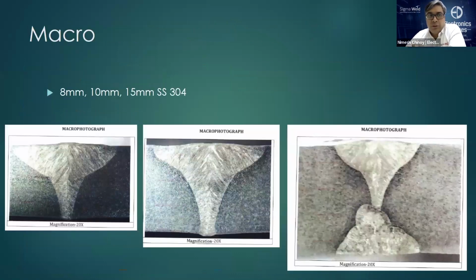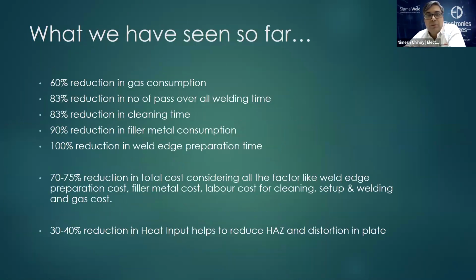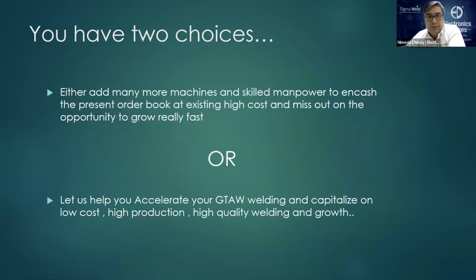Some of the macrographs for 8, 10, and 15 millimeters. If you see, 10 millimeters is in a single pass, 15 is done in 3 passes, 1 on the top, 3 on the bottom, total 4 passes. So that's all that I wanted to present on the speeding up of standard processes.